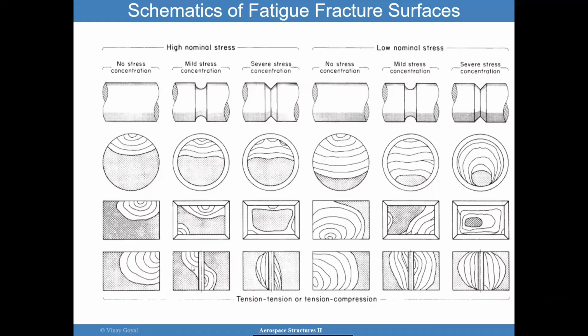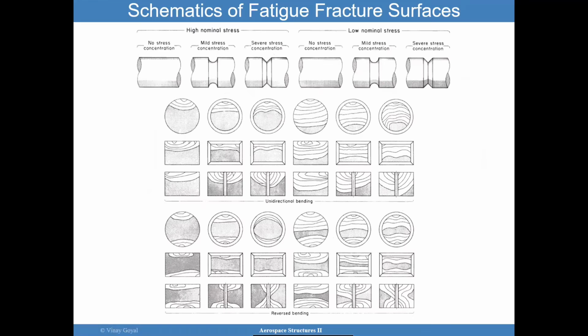and if I were to have a keyhole situation, you're looking at stress concentrations now more concentrated towards the keyhole. But in general, again, the same idea, beach marks and then final fracture. And what you don't want to do is confuse the initiation points because it can throw your failure investigation towards some sort of distraction.